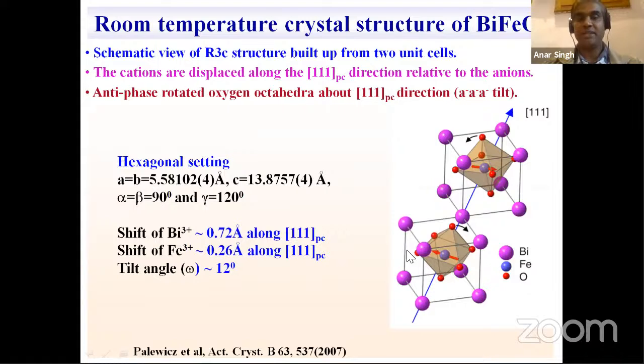So this is the schematic view of the structure of bismuth ferrite, which is basically a perovskite structure, in which the cations and anions move with respect to each other along the 111 pseudo-cubic axis, and two consecutive octahedra along the 111 axis rotate in anti-phase opposite to each other about this axis. This structure belongs to the rhombohedral structure in the R3C space group with A minus A minus A minus tilt system, and these are the shifts of cations in the bismuth ferrite structure, and this is the tilt angle.